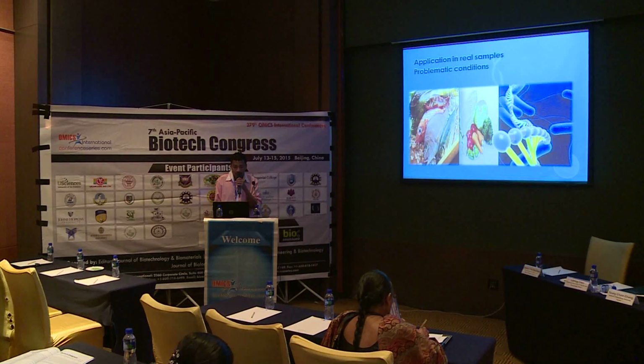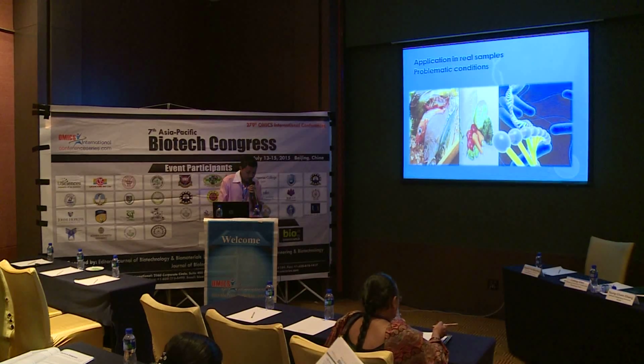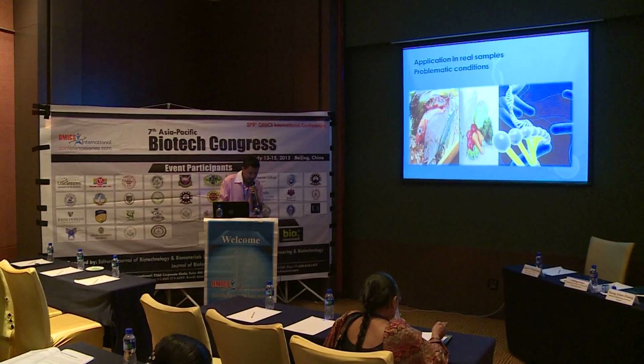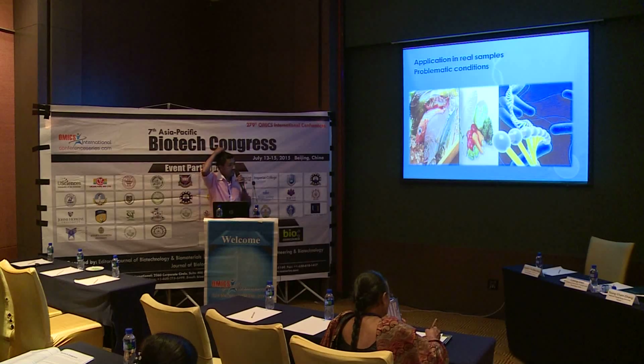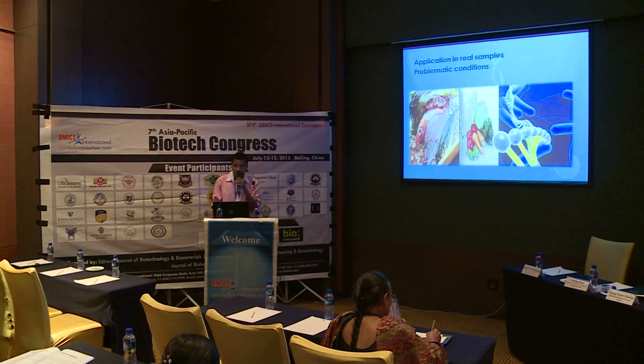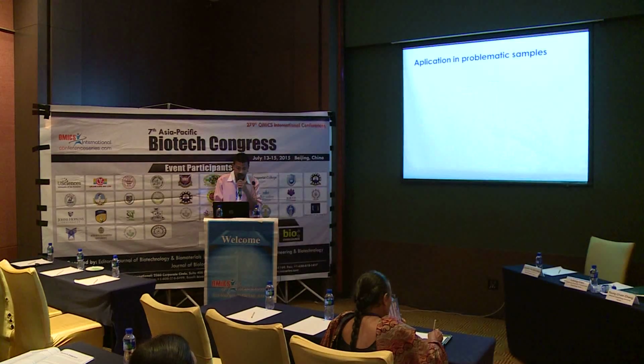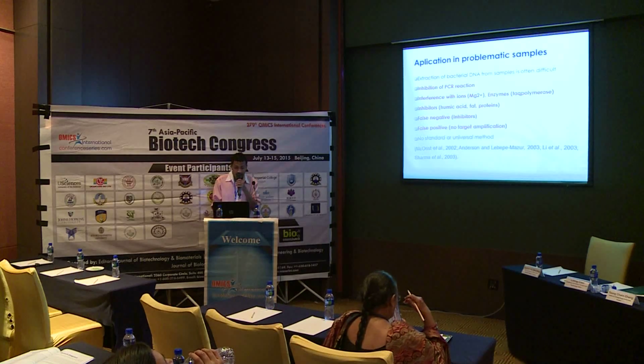So we use application in real samples. It's like a problematic sample. Why do we use problematic samples? Because in reality, in the experiment, we can get many problems. So we use problematic samples because they have some protein or something like that. In the application to problematic samples, we did extraction of bacterial DNA from the sample, and also the problem is inhibition of the PCR reaction. As we know, we need to do purification very well, and also some inhibition gives false negatives.